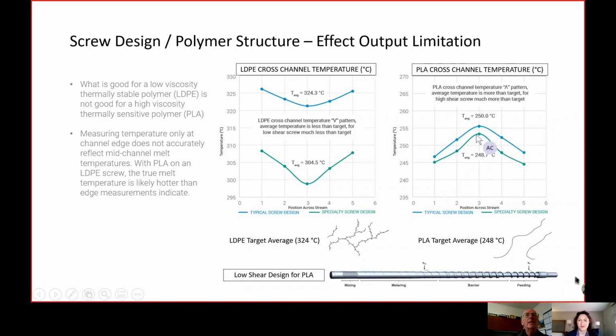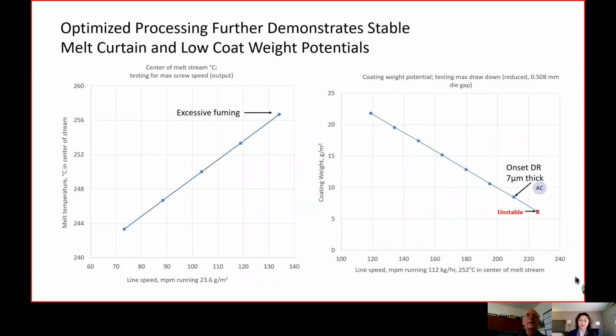When we put the PLA on these same screw designs, with a profile set up to get an objectively lower temperature, what we find is the screw over shears and we get a high temperature in the center. And this is because of the difference in the polymer structure. The linear polymer and the viscosity tend to push this temperature up through the work. When we put in the low shear screw, we shifted that temperature down, but we still see an overheating in the center. So we also did a further adjustment of the screw design, and you can see here, when we add this further adjustment, we were able to further lower that temperature and reduce the overheating in the center of the screw. The data that we're going to talk about further now is on the screw before this additional modification, and I'll let Andrea go over the further data here.